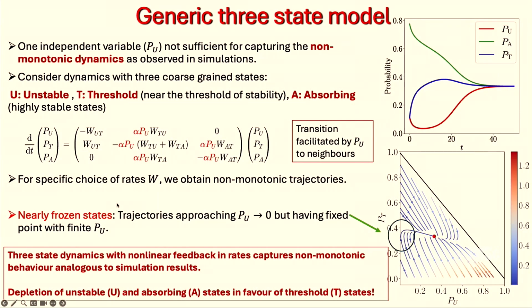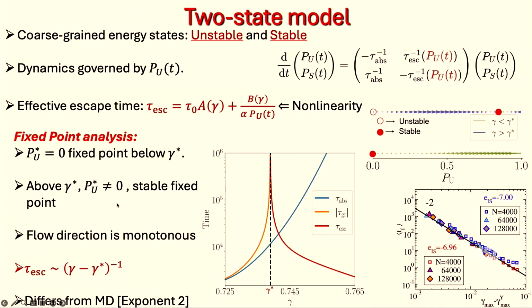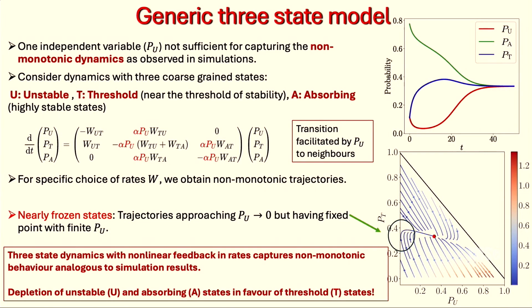Then we said, one thing that this two-state description will not give is any kind of a non-monotonic dependence of the state of the system with respect to the number of cycles, because the description of the system is not rich enough. So we said let's go to the next minimal description, which is a three-level description where I have unstable and stable states, and I also have a new category which is the threshold states.